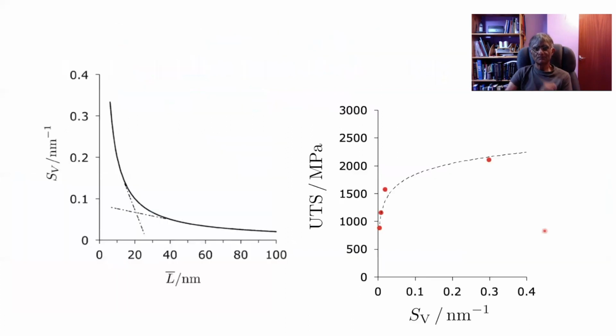Okay, let's think about what nanostructure actually means. Now, if I measure the grain size using a mean linear intercept, then if you recall the lecture on pearlite, the amount of surface per unit volume is equal to 2 divided by the mean linear intercept. So this is plotting here the amount of surface per unit volume, and this is in nanometers to the -1. But a value around here corresponds to about 100 million square meters of interface in 1 cubic meter of material.